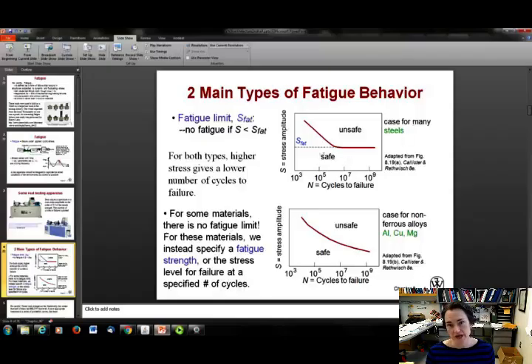Okay, so next, what you see with many steels is that for these steels, as long as you keep the stress below what's termed a safe level, the part won't fail on you, okay? So you have to keep it at a low stress. And then you're in this safe region here, because the curve will flatten out as it approaches high numbers of cycles. So as long as you keep it below that stress amplitude, then the part will perform well. Okay, that's a steel type behavior.